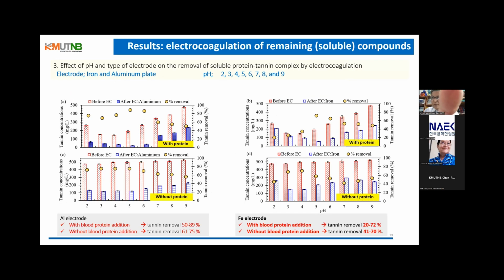After separating the insoluble protein tannin complex by centrifugation, the suspension was subject to electrocoagulation to remove the remaining tannins. This figure shows the removal efficiency of tannins using electrocoagulation with aluminum and iron electrodes at an initial pH between 2 to 9, electrolysis time of 30 minutes and current density of 20 milliamp per square centimeter. When using aluminum electrode, the tannin removal reached 89%.